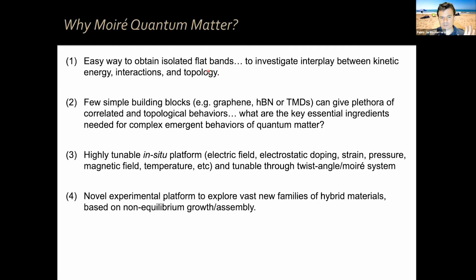Now, the other thing is that with a few simple building blocks, for example graphene, hexagonal boron nitride, or transition metal dichalcogenides, you can have a range of heterostructures that give you a plethora of correlated and topological behaviors. Which brings up the question of what the key essential ingredients are for complex emergent behavior of quantum matter. Because to some extent, we can get rid of a lot of chemistry by using these very simple blocks and still obtain the type of behavior more typically associated with very complex chemistry. Now, this platform is highly tunable in situ.